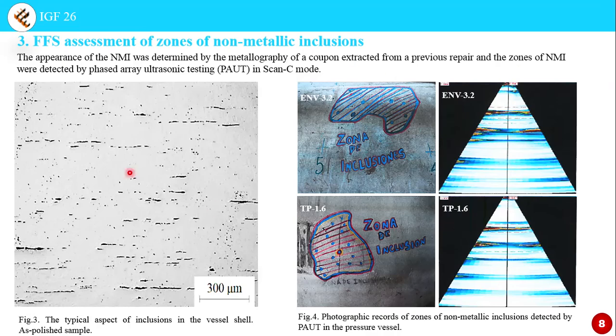Here in this slide, you can see the nature of non-metallic inclusion zones of the assessed pressure vessels. You can see closely spaced non-metallic inclusion zones, and we can consider them as laminations. And also here you can see two examples of non-metallic zones detected by PAUT scan records. One is close to a weld joint, this zone is so close to the weld joint, and another is isolated.